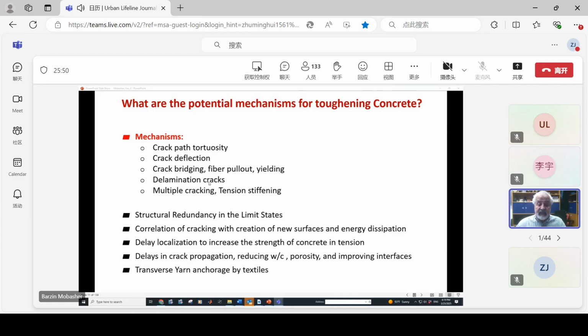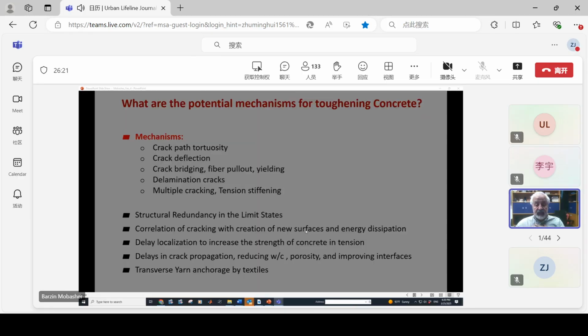And delamination cracks are perfect. At the same time, multiple cracking, tension stiffening effects, and such, all of them become present, and they take energy out of the system. So that gives our structure a redundancy. We can go toward plastic limit states, and we can actually do the correlation calculations of how much more energy is needed to create all these new surfaces, to create all of this energy dissipation. And that's how we can actually increase the strength of concrete in tension.